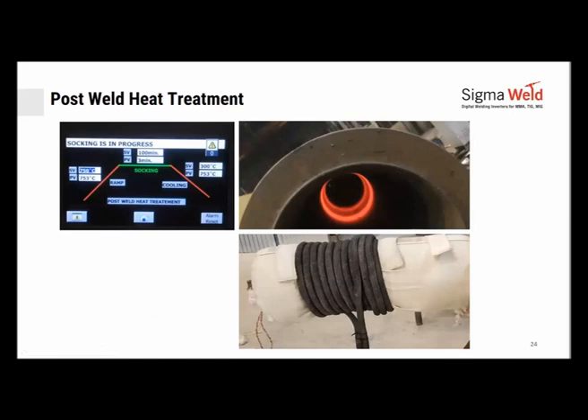Similar job here being done for post heat. We had to achieve a temperature of 750 degrees. As you can see, it's achieved the 750 degrees after ramp. It is undergoing soaking for about 100 minutes, and then it will come down to 300 degrees in again a controlled slope of 40 or 50 degrees per hour. This is the way the job is wound. This is a blanket, the Ceravol blanket, and on top of it they have wound the induction coil. Here you can see the profile of heat generated on the inside.